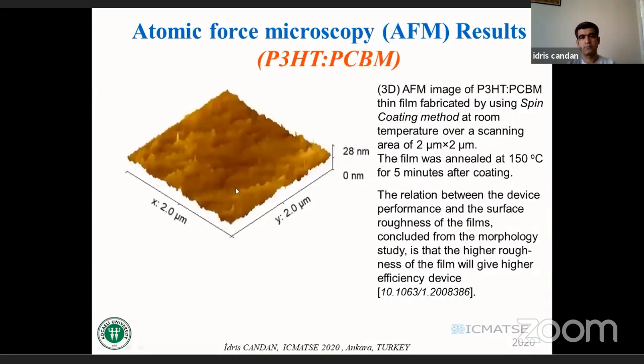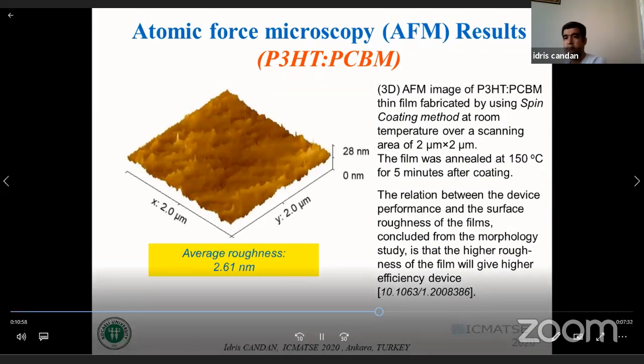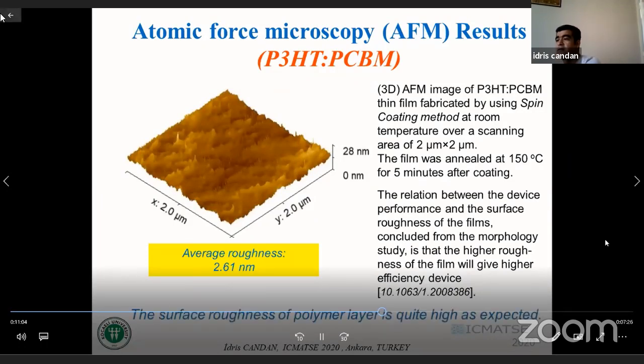And here you can see the AFM image of the PCBM in 3 dimensions over the scanning area. The relation between device performance and the surface roughness of the films concluded from the morphology study is that high roughness of the film gives higher efficiency devices. Our average roughness is found as 2.61 nanometer. The surface roughness of the polymer is quite high as expected.